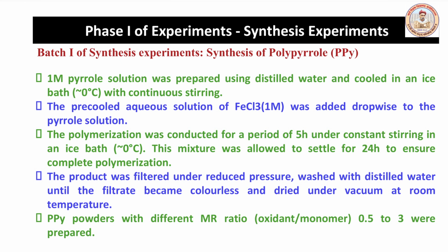The first batch was the synthesis of polypyrrole. A series of reactions were conducted to prepare the black polypyrrole powder. The procedure in short is like this. 1 molar pyrrole solution was prepared using distilled water and cooled in an ice bath with continuous stirring. The pre-cooled aqueous solution of FeCl3 was added dropwise to the pyrrole solution. The polymerization was conducted for a period of 5 hours under constant stirring in an ice bath. The mixture was allowed to settle for 24 hours to ensure complete polymerization.